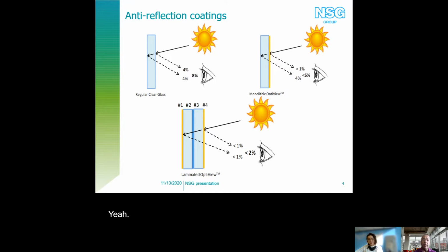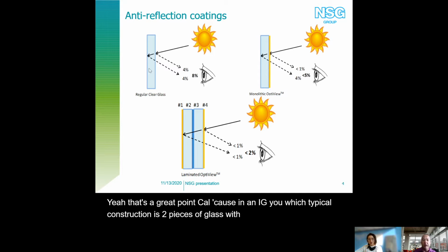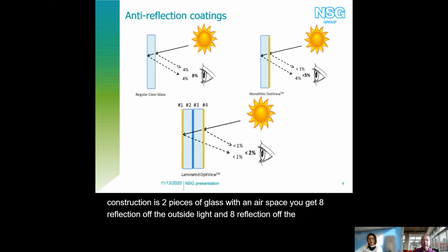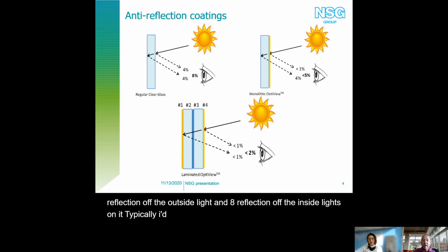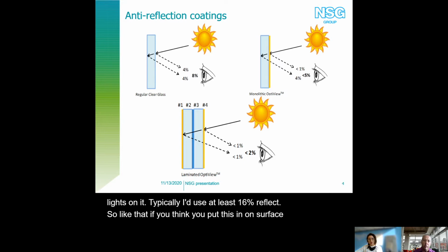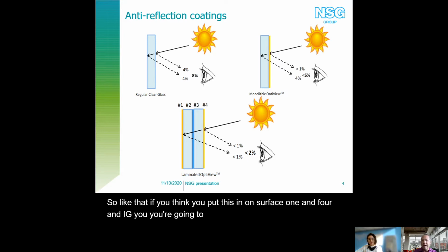Yeah, that's a great point, Kayla, because in an IGU, which is typically two pieces of glass with an airspace, you get 8% reflection off the outside light and 8% reflection off the inside light. So typically an IGU is at least 16% reflective. If you think you put this on surfaces 1 and 4 in an IGU, you're going to go really low, you're right, it doesn't, because you've got to have it on a laminate, or you have to have it on all 4 surfaces to really get that super low reflection.